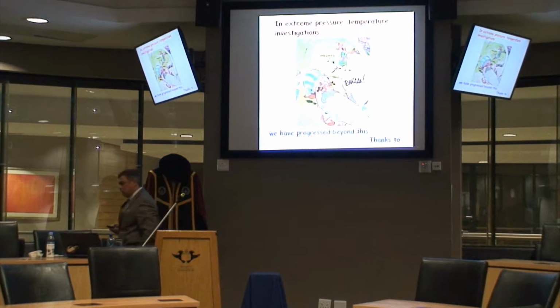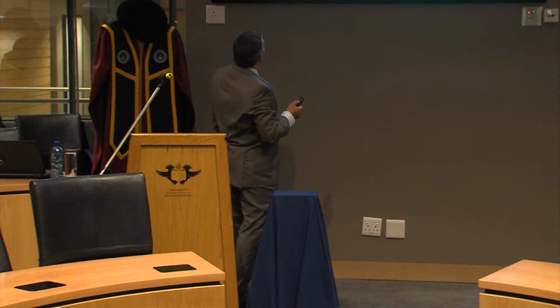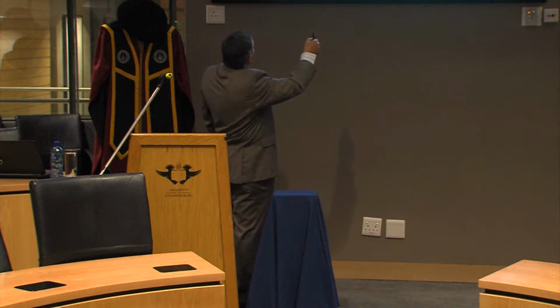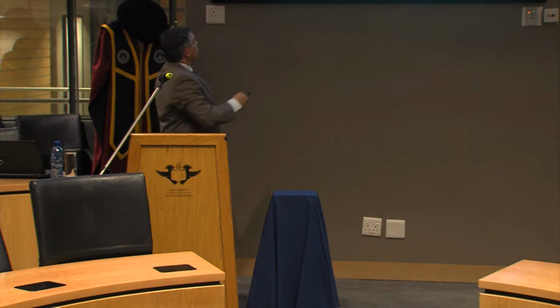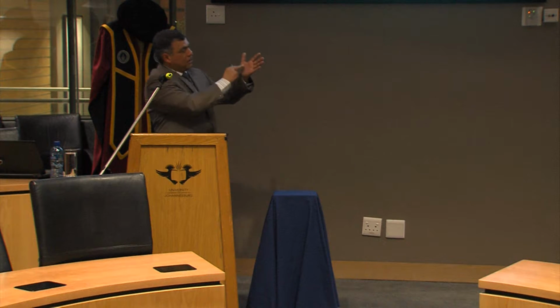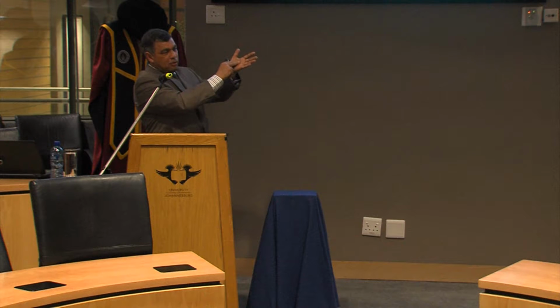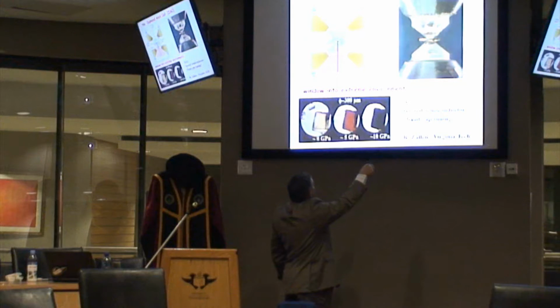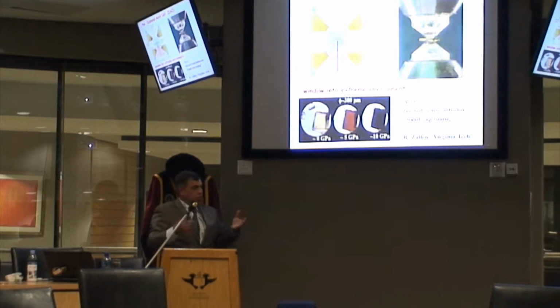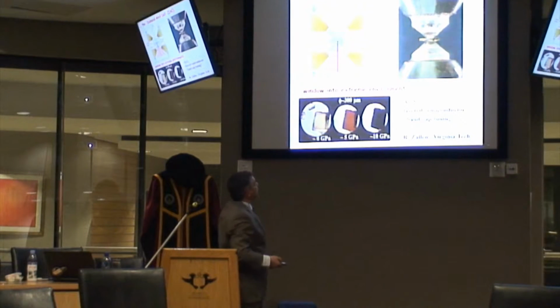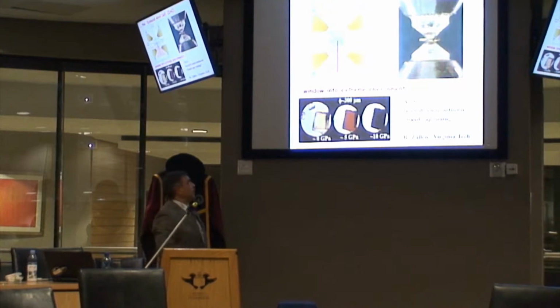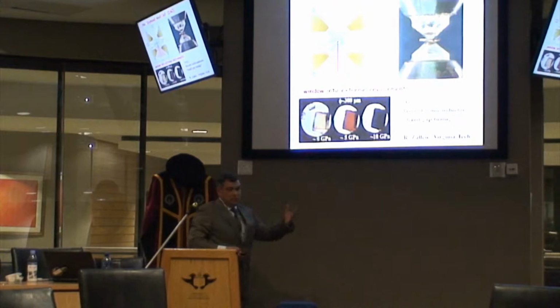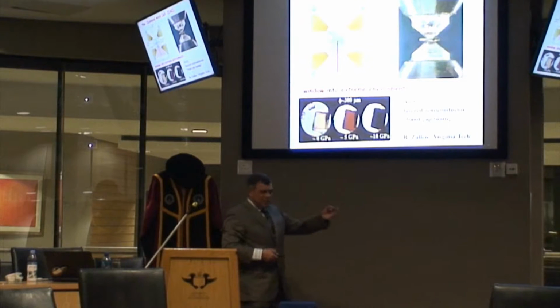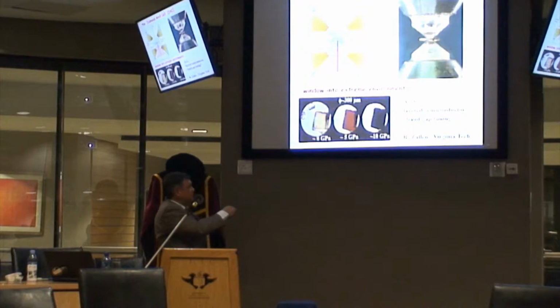Now, if you want to generate these extreme pressure temperature environments, this is not the way to do it. In fact, this is the way you go about doing it. You use a diamond anvil cell. Two diamonds, polish off the tips to get what we call diamond anvils, and then get for yourself a metal foil, drill a hole into it, insert your sample into the hole, and squeeze that between the diamonds to have a configuration like this. The important thing is that the diamond is hard, so you can apply reasonable, substantial forces, and most importantly, you can view through the diamonds into the cavity. And you can generate very high pressures of hundreds of thousands of atmospheres because you can apply substantial forces over very small areas.